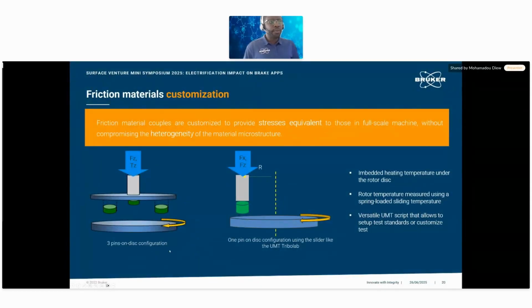Two configurations are possible: 3 pins on disk or 1 pin on disk, depending on what you're expecting to run. 3 pins is more stable, 1 pin is something simple for testing, but both can be run. The only influence that we see currently is that when you run 3 pins, you will get heating of the system due to the increased surface, and you will get 3 times the load that you get here. And when you only run 1 pin, the temperature will be really lower.